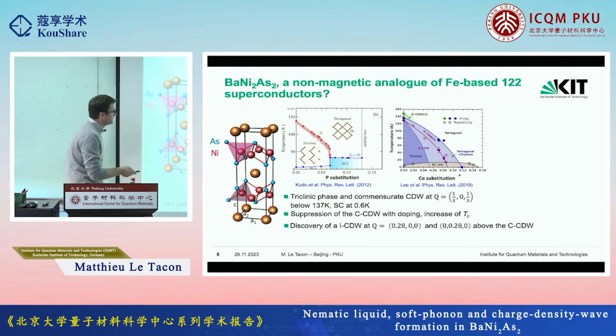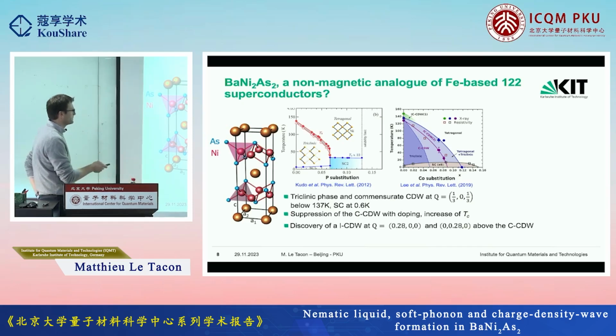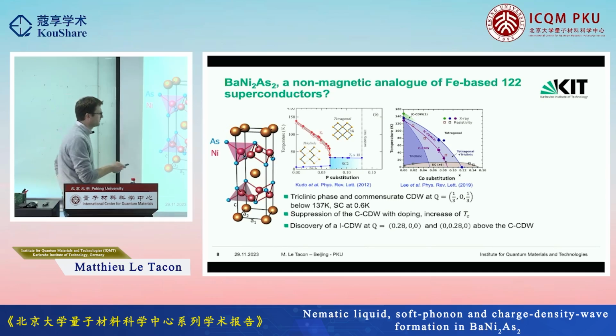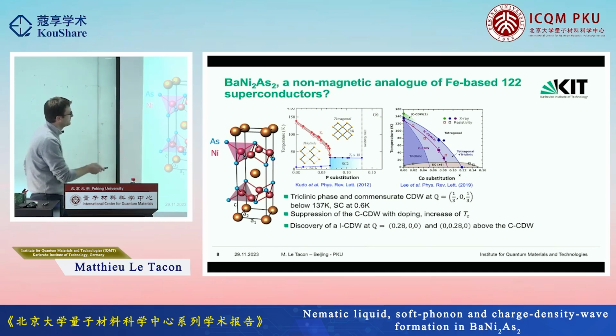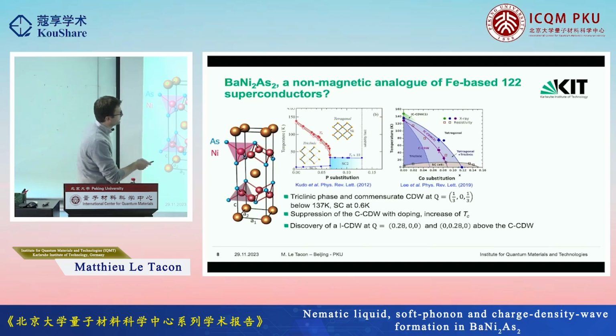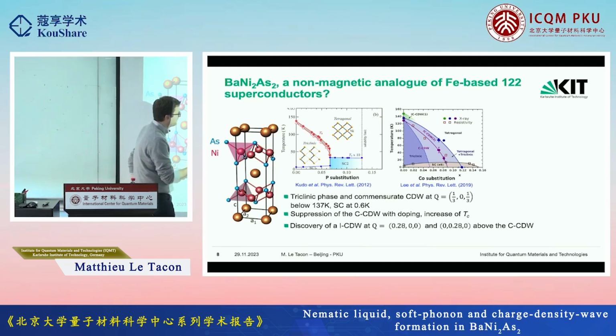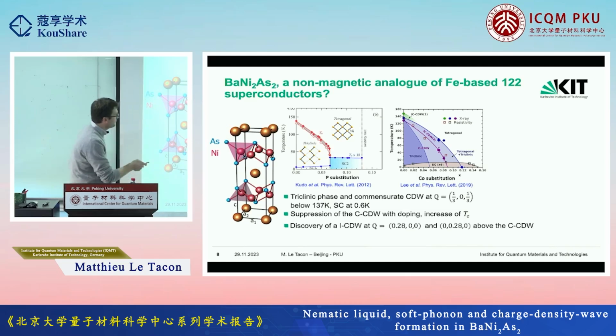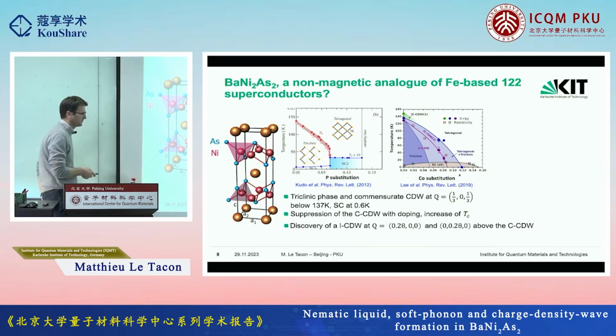It has superconductivity already at 0.6 Kelvin, which is different from the iron-based superconductors. But what's interesting is that when you suppress this triclinic phase using, for instance, phosphorus doping or cobalt substitution, you have somewhat of an enhancement of the critical temperature, which goes from 0.6 Kelvin to 3.5 Kelvin, something like that. So it's still a very low TC,